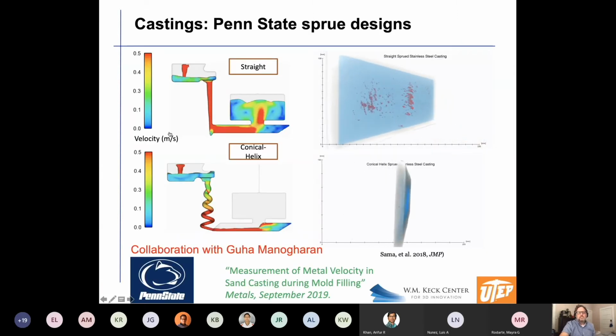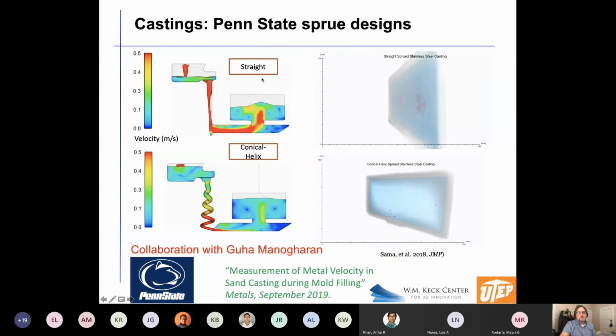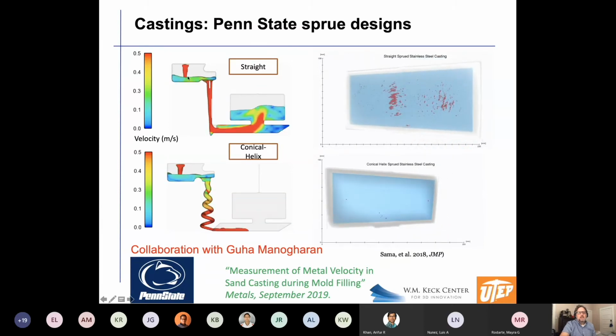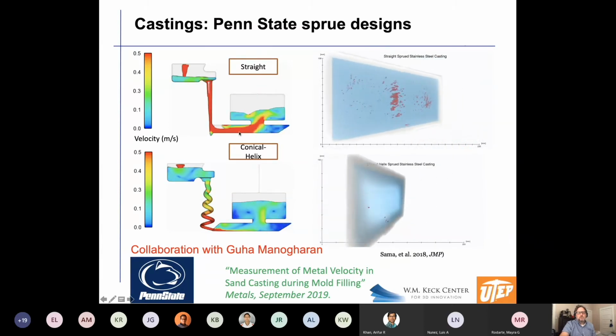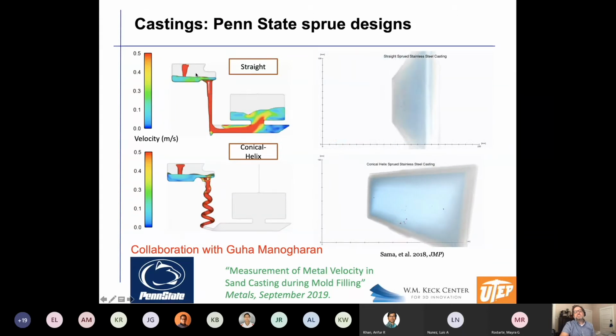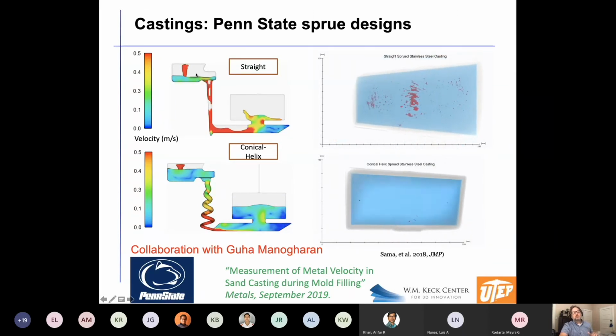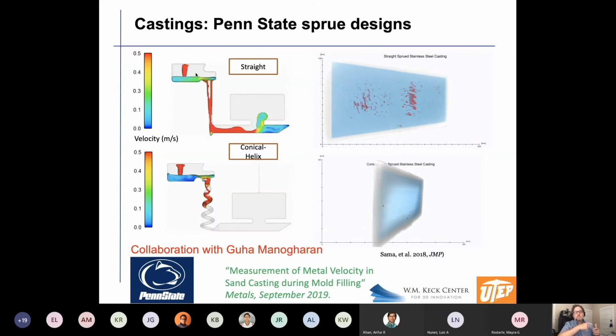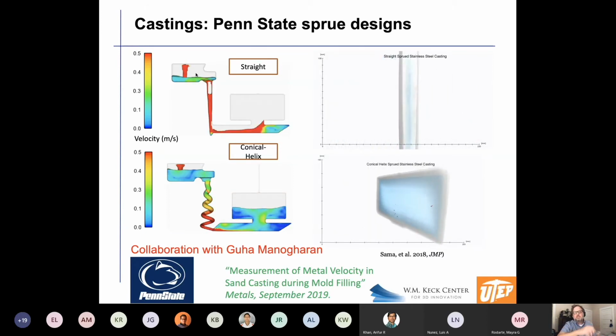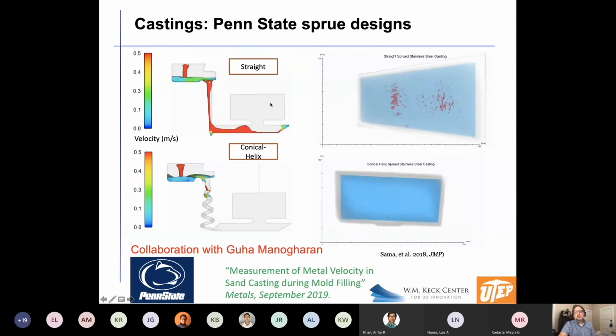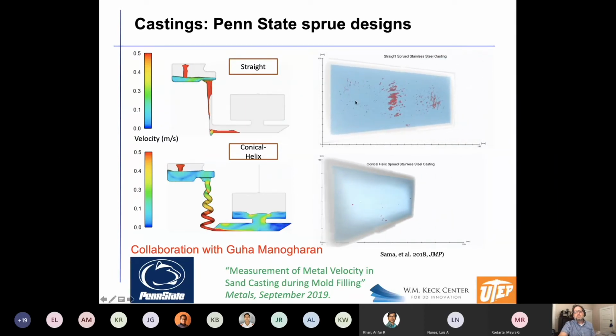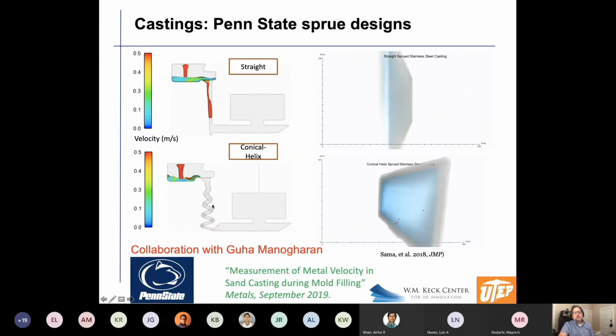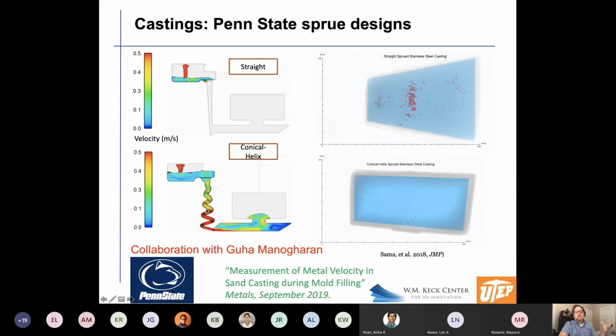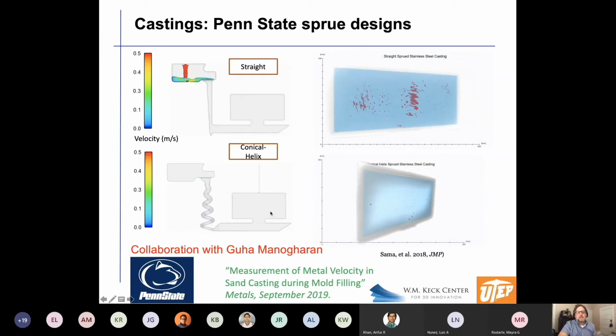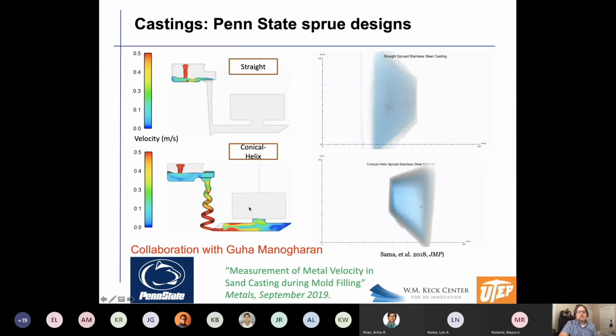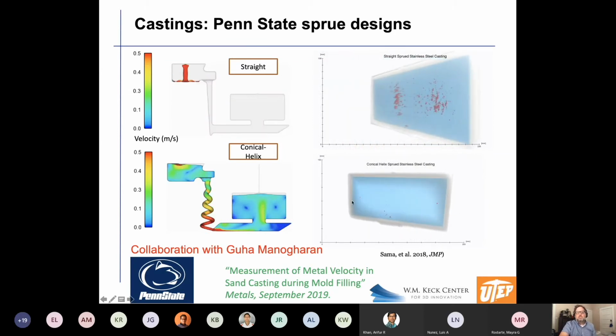Here's a project with Penn State. Now this is simulations of 2 molds, a traditional mold. This is a casting, and this is a sprue, and this is the sprue and the gating system. And the color is the speed of the metal. And you don't want metal to go fast because there's turbulence, air entrapment, and it causes porosity. And you can see in the CT scan here that this doesn't do very well. Here, Guha Manogharan basically does a helix, and he throttles back the velocity, and it fills up at about half the speed, but it fills up slower and with much less porosity.